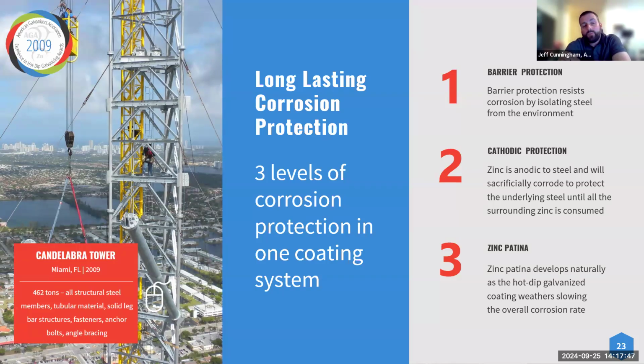Next, and the most important one, is the third level of the zinc patina. This is zinc hydroxides and zinc oxides building up on the surface over time. All metals do create some sort of patina. You know, the most common one, copper, it kind of turns that green color. That's the patina developing, where it just naturally goes through wet and dry cycles, and it builds up this zinc hydroxide on the surface, and it really slows the overall corrosion rate, because it's like